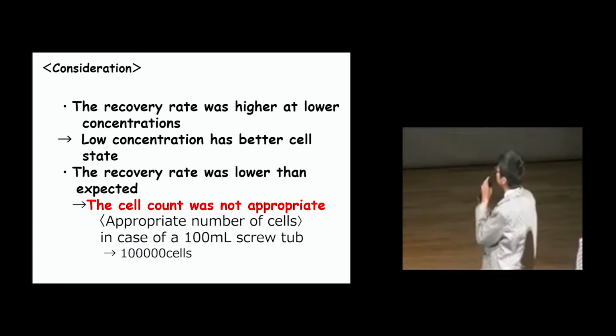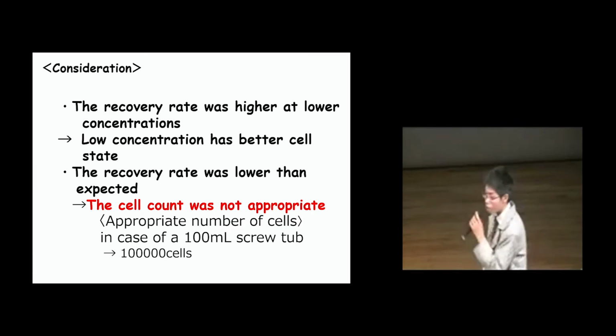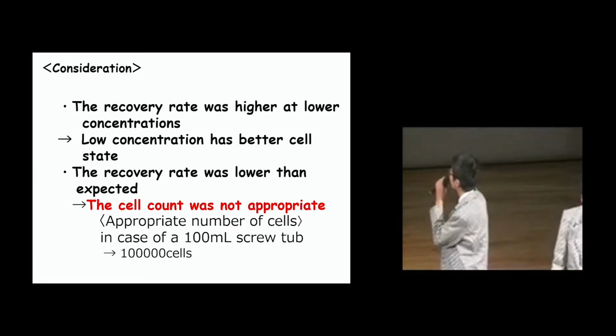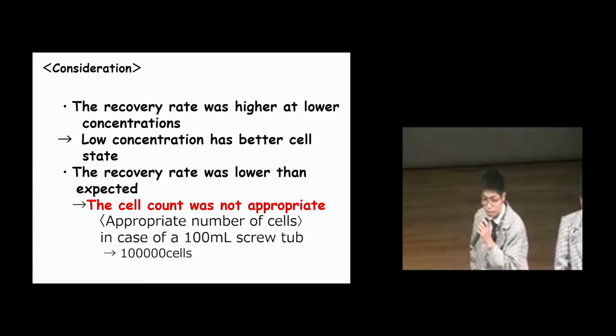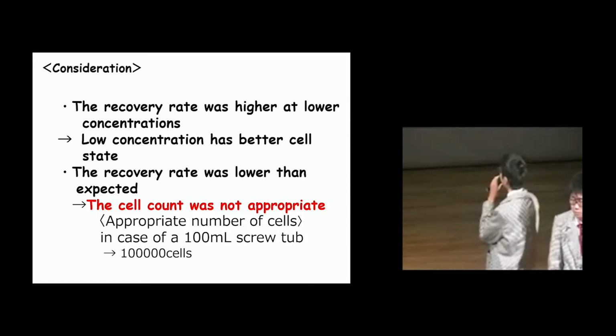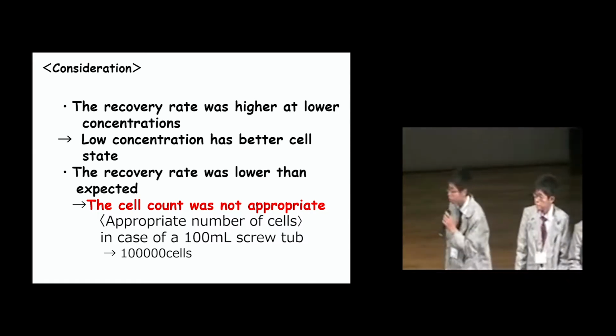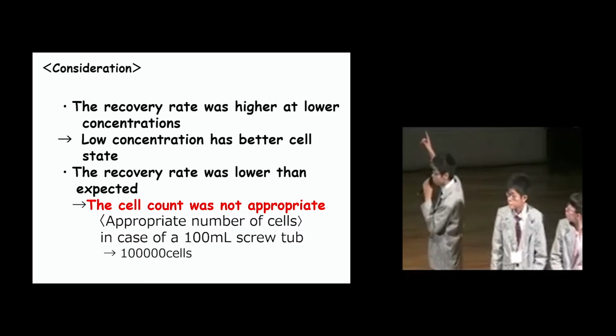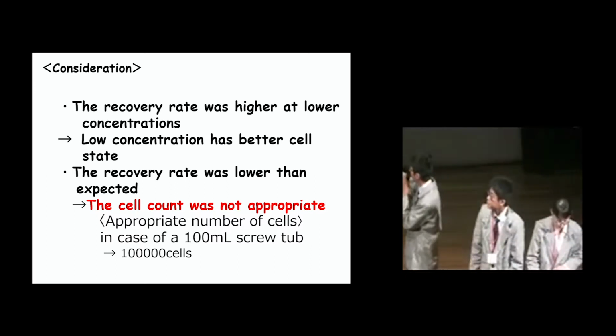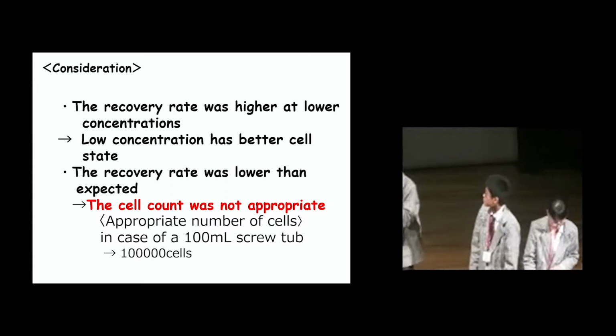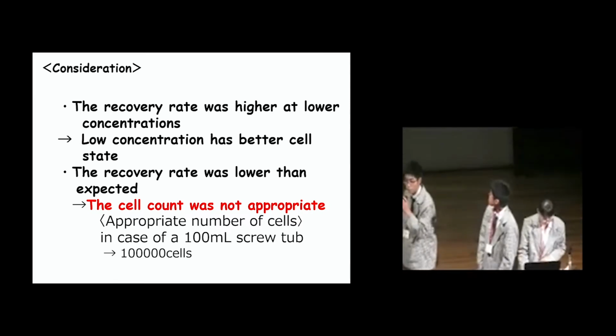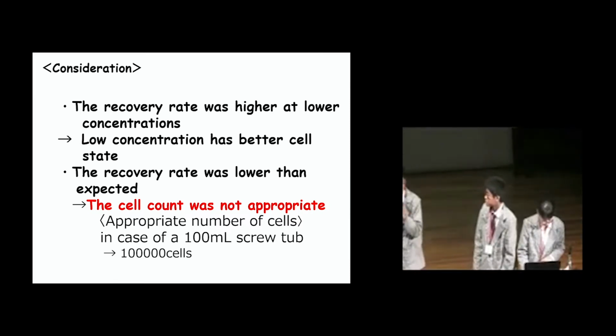Consideration. The recovery rate was higher at lower concentrations. Low concentration has better cell states. The recovery rate was lower than expected. The cell count was not appropriate. For an appropriate number of cells, in the case of a 100 milliliter screw tube, there should be 100,000 cells.